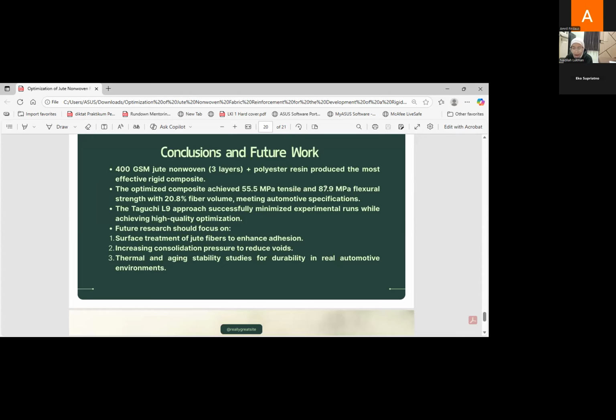In this paper, the conclusion is that 400 GSM jute nonwoven in three layers plus polyester resin produces the most effective composite. The optimized composite achieved 55.5 MPa tensile and 87.9 MPa flexural strength with 20.8% fiber volume, meeting automotive specification.